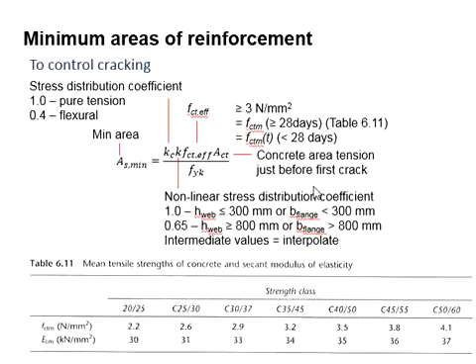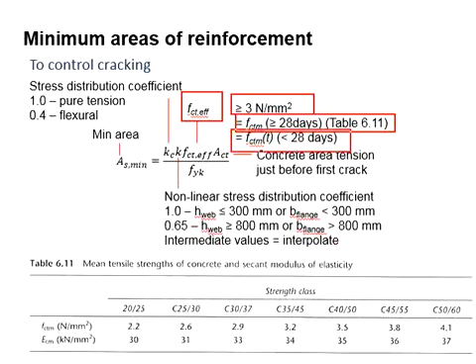The tensile cracking strength of the concrete is assumed to be greater than 3 N/mm². And it can also be assumed as the fctm for the concrete age more than 28 days, or you can calculate the fctm for the concrete which is immature according to the age of the concrete.